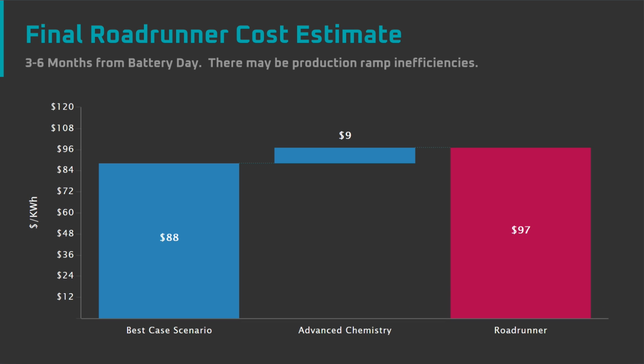If Tesla does reveal a high energy density, long cycle life battery cell at Battery Day, then it will likely add cost to the $88 per kilowatt hour I targeted earlier. CATL's estimate of a 10% cost increase for a million-mile battery chemistry is likely the most accurate information we'll find. Adding 10% cost at the cell level to the $88 per kilowatt hour pack level estimate from above would result in a battery around $97 per kilowatt hour at the pack level.